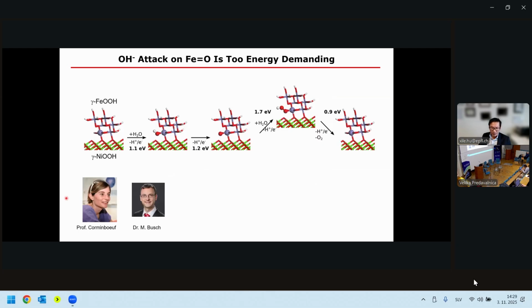Our colleagues in our department on computational chemistry looked at the iron catalyst. If you have gamma iron OOH, this is not a really good catalyst, and everybody knows about it. According to calculations, going from iron to iron oxo species by oxidation is quite easy. The difficult step is the hydroxide attack on the iron oxo to make the iron OOH species. According to their calculation, in terms of energy it is already too high, and then the release of oxygen is quite easy. This is why everybody knows that pure iron is not a really good catalyst.